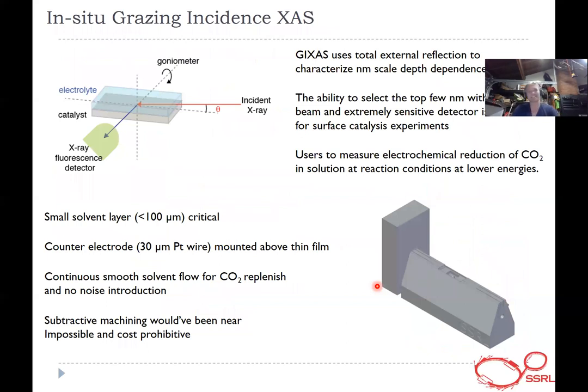We also do grazing incidence XAS. Grazing incidence is a surface sensitive technique. It uses total external reflection. So your X-ray is basically bounced off, and the evanescent wave created allows you to probe the top few nanometers of your sample. So this is great for interfacial experiments, surface sensitive experiments. You can do depth profiling with this.